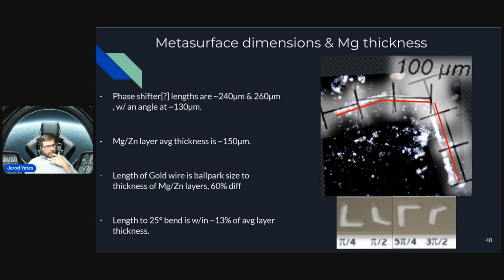Well, that's really interesting, because the average layer thickness of the magnesium and zinc is 150 microns. I might just be noticing things that aren't there. Maybe there's no relationship between the lengths of these arms and the thicknesses of the magnesium layers. But it's in the ballpark. The overall length of those is quite different, at 60%. But that little 25-degree bend there, if we look at that length, if that's important, that's within spitting distance of the average thickness of these layers.